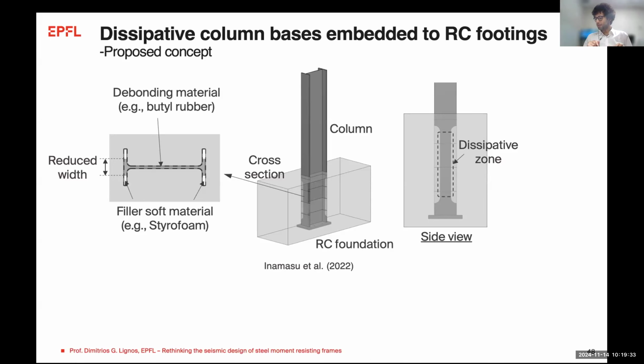One thing that I want to ask you is about strain rate effects, because I believe in your experiments, you did mainly quasi-static testing. And in some of the finite element models, later on when you did nonlinear time history analysis, based on my experience, kinematic hardening doesn't change much with the strain rate, but isotropic hardening might change a lot because of the heat effect and stuff like that. But I want to know whether you considered the strain rate effects in your models.